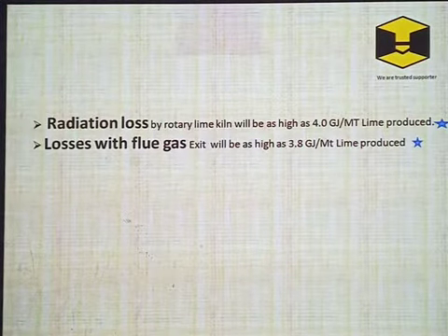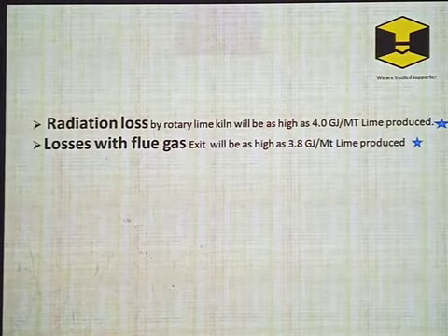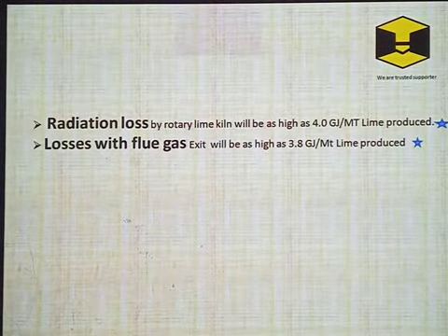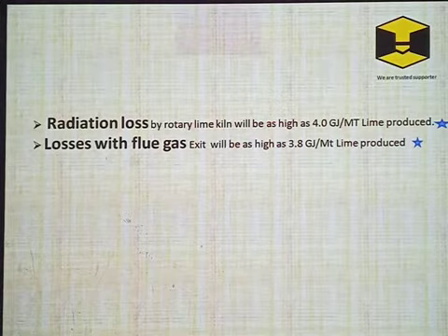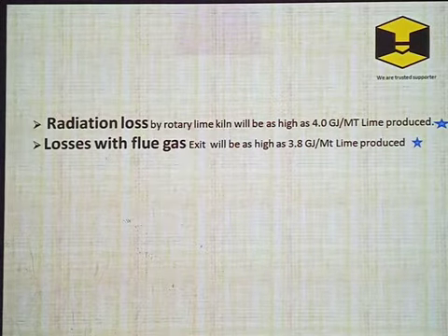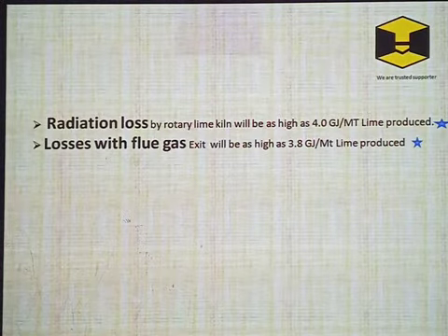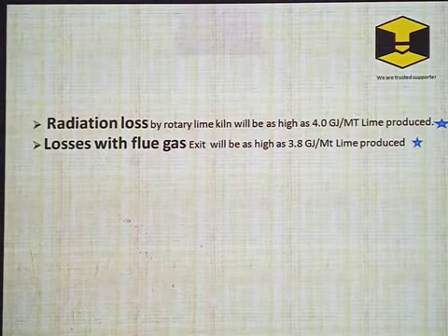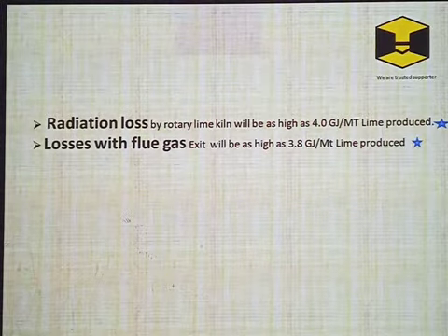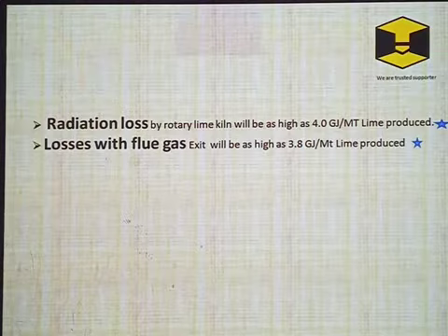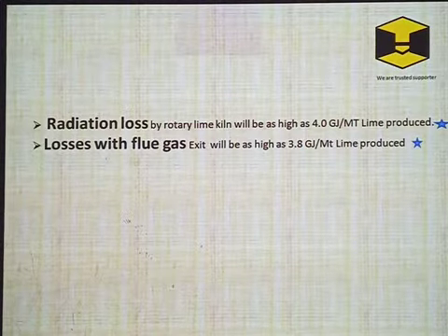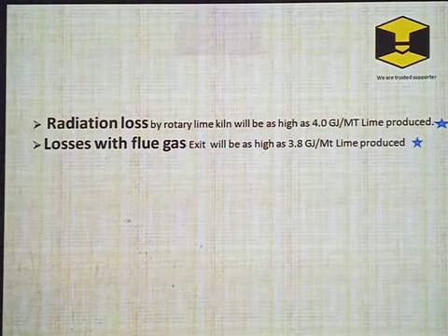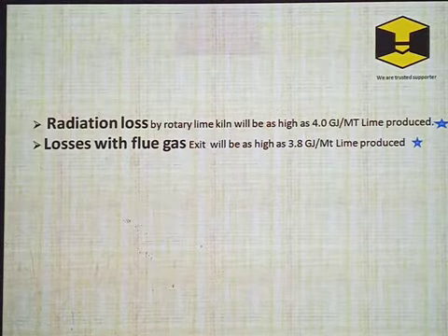Radiation losses from rotary lime kiln surface can be as high as 4 gigajoule per metric ton lime produced, and if you will see, it is more than the theoretical energy required to produce a metric ton lime. Similarly, heat losses through the flue gas can be as high as 3.8 gigajoule per metric ton. This is also more than the theoretical energy required to produce a metric ton lime.